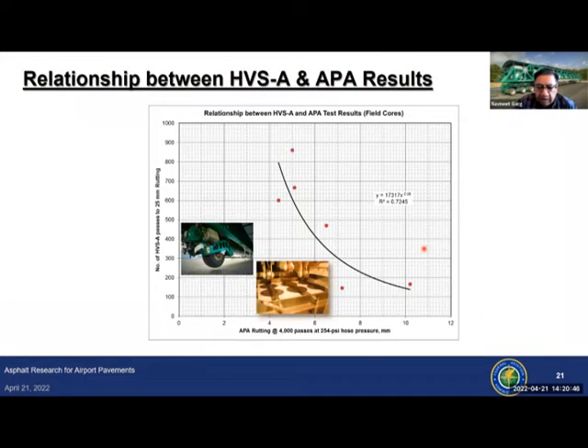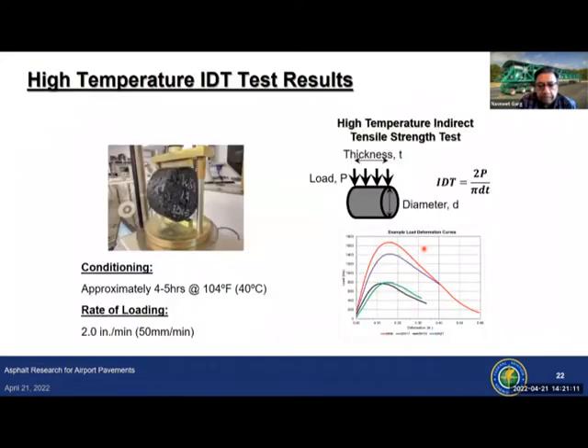We also compared these results with full-scale tests under HVS. So on the y-axis is the number of HVS passes to get 1 inch of rutting. That is our failure criteria in full-scale tests. And on the x-axis, you see APA rutting at 4,000 passes at 254 PSI hose pressure. So you can see there is a trend that you can use APA data to predict rutting performance.